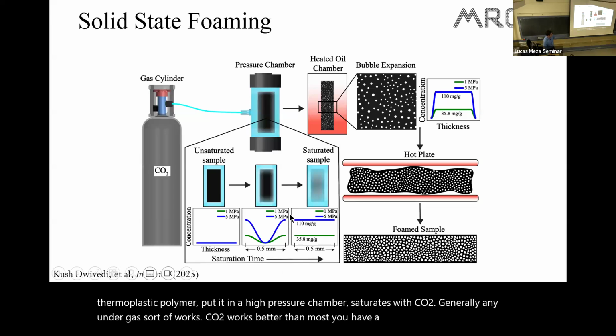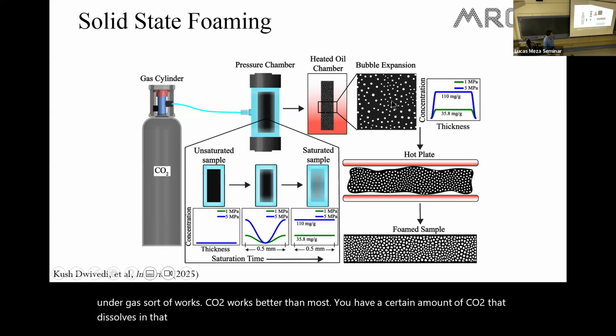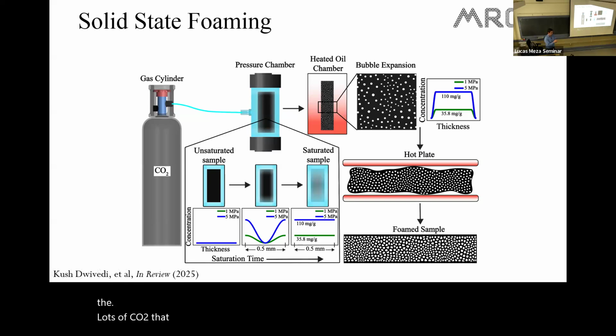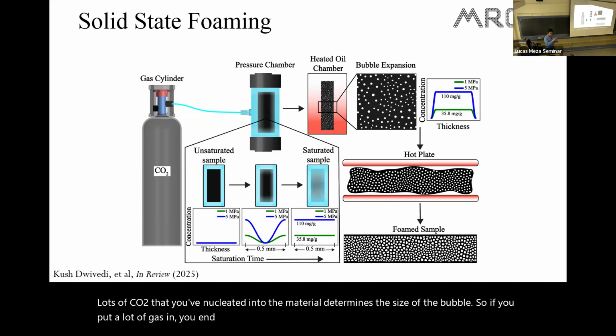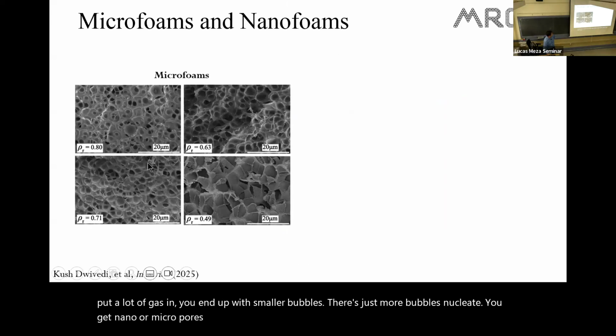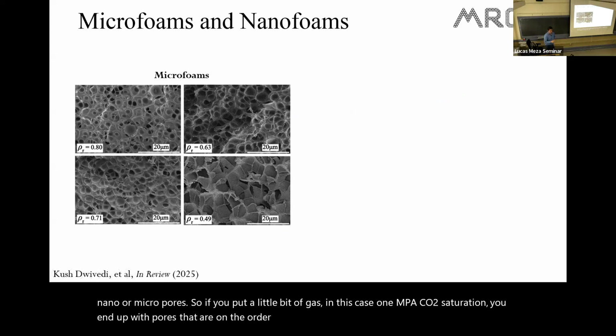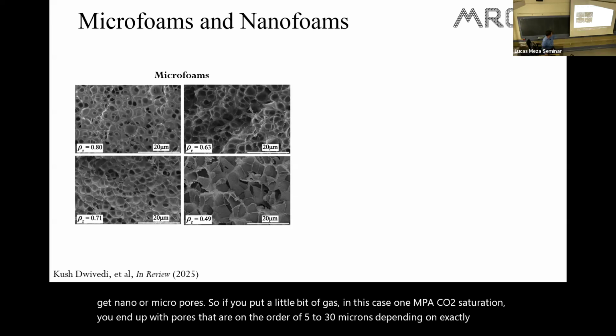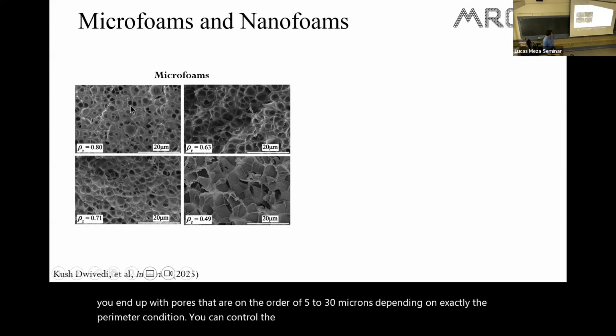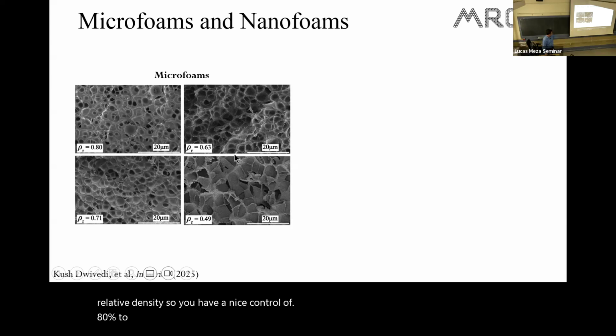You have a certain amount of CO2 that dissolves in that material. You take it out, heat it up, and the dissolved CO2 nucleates as bubbles. The amount of CO2 that you've dissolved into the material determines the size of the bubble. So if you put a lot of gas in, you end up with smaller bubbles. There are just more bubbles nucleating. You get nano or micropores. So if you put a little bit of gas in, in this case 1 MPa CO2 saturation, you end up with pores that are on the order of 5 to 30 microns, depending on exactly the parameter condition. You can control the temperature of the foaming process and control relative density. So you have nice control of 80% to 50% dense foams.